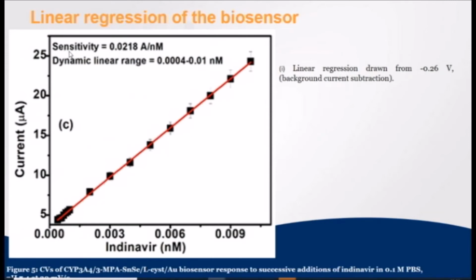We can see that we have obtained a sensitivity of 0.0218 and a longer dynamic linear range because we have added more than 10 concentrations. It is very important when you're coming up with your biosensor system to use a variety of concentrations. And you go lower, because most of the time when you start with a higher concentration, you might reach a saturation point easily.